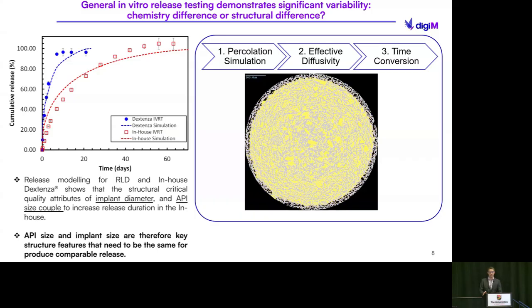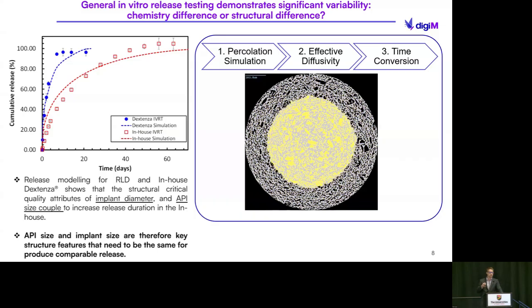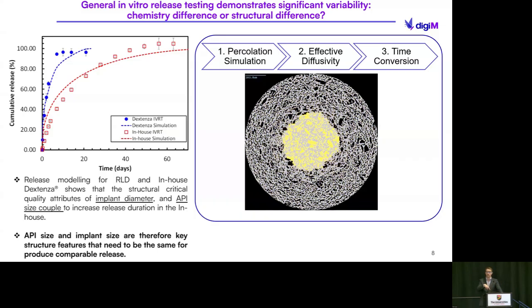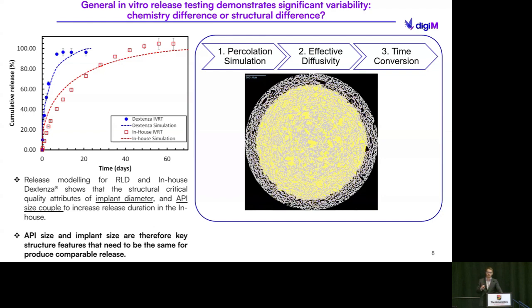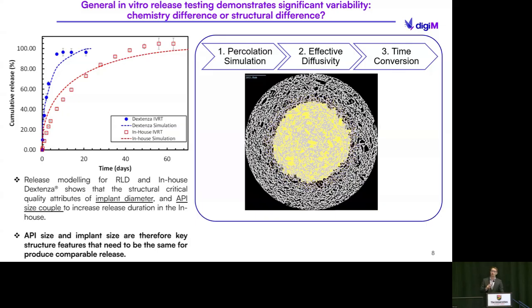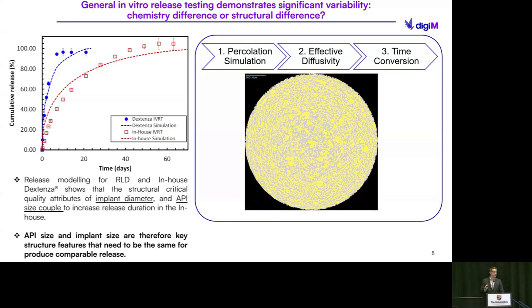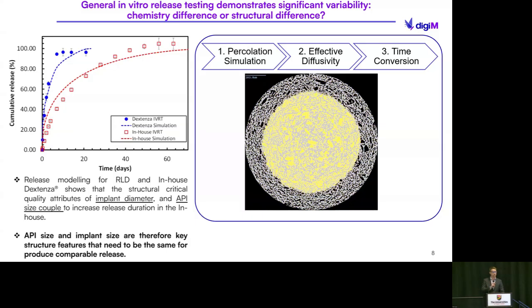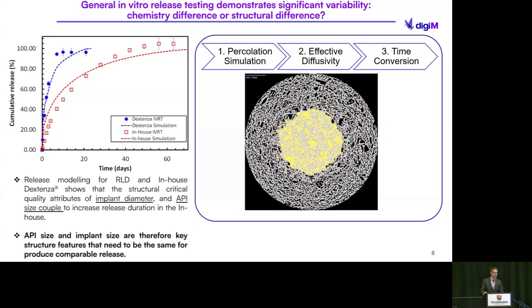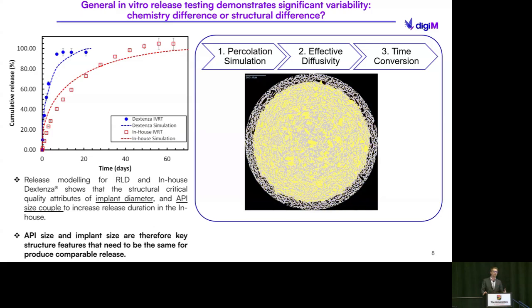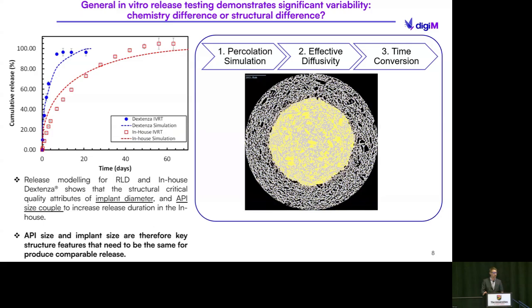And most importantly here, when it comes down to consideration of those long pores that we saw in the RLD, we didn't include the pores as a transport phase. So at no point in our simulation did we include anything to do with those pores, which strongly indicates that in the process of swelling inside of the canal, those pores likely close up and you no longer have those features to worry about.